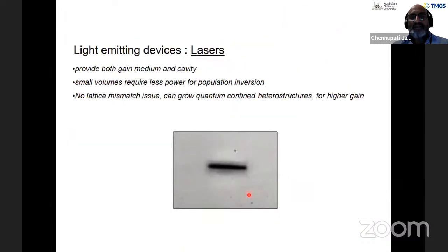It turns out if you take a nanowire and shine light from the top, light starts coming from both ends of the nanowire, which acts like a waveguide. Of course, you need to choose the right kind of nanowire and dimensions and other things, which I'll come back to. But also because of the large refractive index difference between the nanowire, which is 3.4, and the air, with a refractive index of 1, both ends of the nanowire act like mirrors. So I do not need to create any external mirrors.